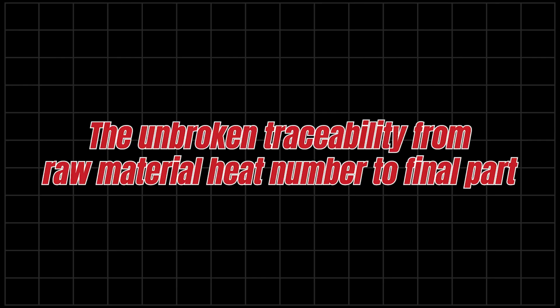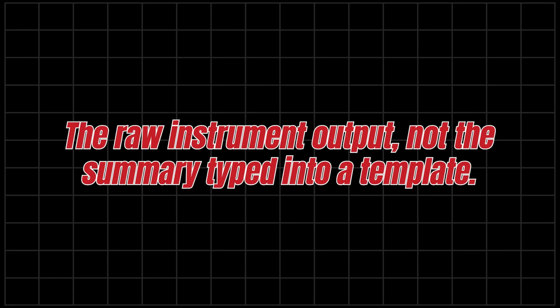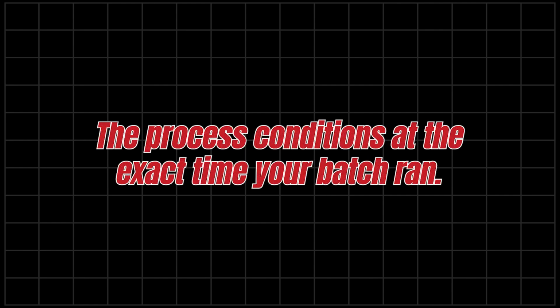Most metallurgical failures I have seen are not about nominal chemistry, they are all about process evidence, or the lack of it. The fingerprint of quality is in the unbroken traceability from raw material heat number to the final part. The raw instrument output, not the summary typed into a template. The process conditions at the exact time your batch runs. If you only collect end-of-line results, you are measuring the lottery. If you collect in-process evidence, you are managing the probability. That's the mindset shift.